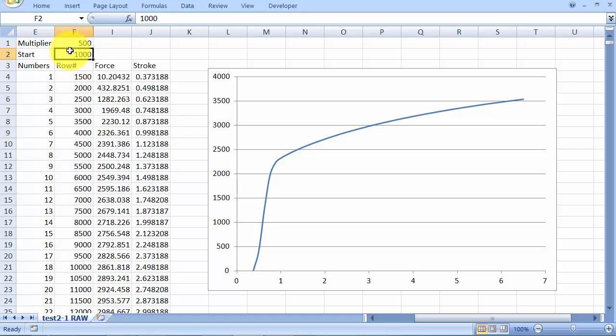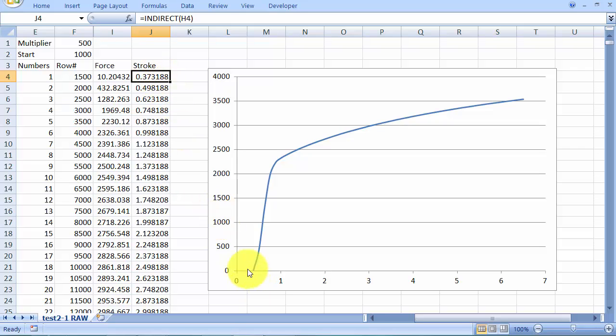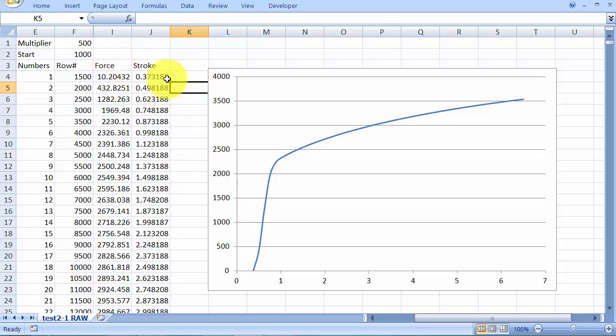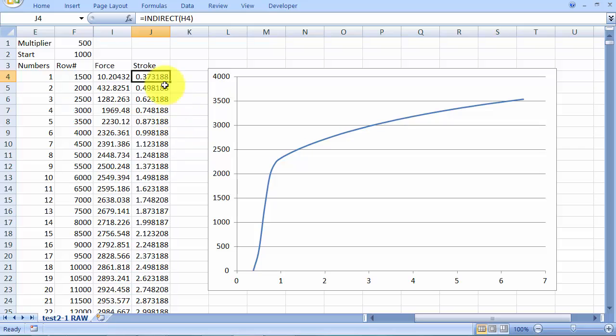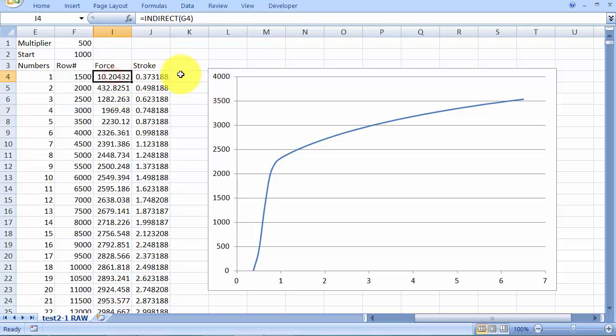And you'll see also if I'm starting at 1500 here, then my force value, my stroke values, particularly stroke is probably the big issue here. It's going to start at some distance, which is away from zero on the graph. So that's just because the machine, when we've started up the tensile tester, it's begun to pull the sample apart. But there's been some slippage in the teeth or there's been some just general movement in the device that has enabled stroke to take place without much force.